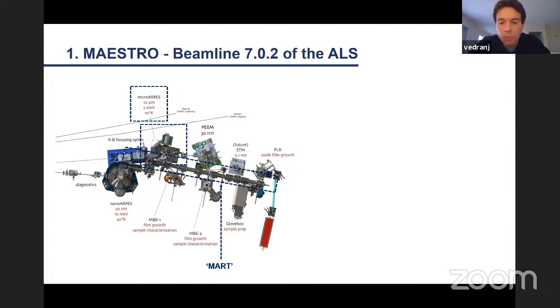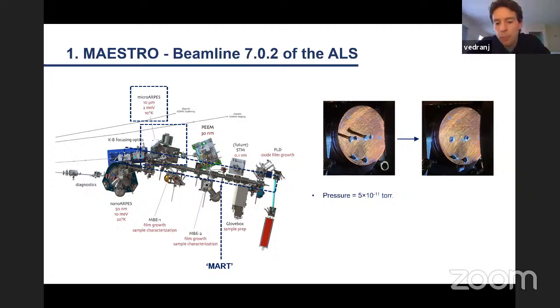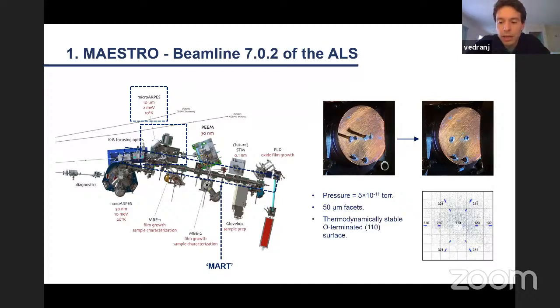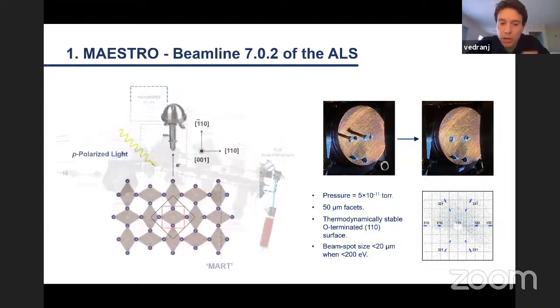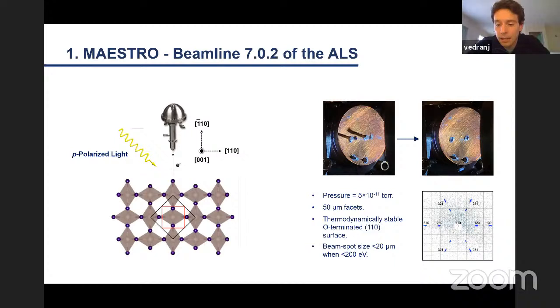We specifically worked on the micro-ARPES chamber. We prepared our samples by gluing a ceramic top pin to single crystals, and within the UHV chamber, we hit these samples and they would reveal a perfectly clean surface of the material, and it was highly reproducible. We were exposing these 50 micrometer clean facets of the thermodynamically most stable, oxygen-terminated 110 surface, and the synchrotron beam in these ultra-high vacuum chambers was on the order of around 20 micrometers or less. So we could really see very tiny domains of the material, and you see the geometry of the experiment with respect to the electron energy analyzer and the light coming onto this 110 surface and how it was oriented.